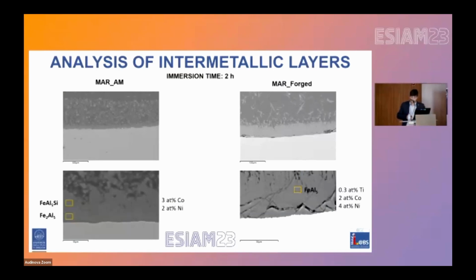Here we can see the scanning electron microscope image of the cross-section after 2 hours of immersion. As can be noted, the intermetallic layer on the maraging forged sample results less adherent to the substrate, and it's characterized by a thickness that is more or less double with respect to that on AM samples. The presence of different alloy elements, however, makes the interpretation of the different corrosion behavior not so easy. According to the EDS analysis, the intermetallic layer on the AM sample is mainly composed of 2 different phases, while only one phase is identified for the forged sample.